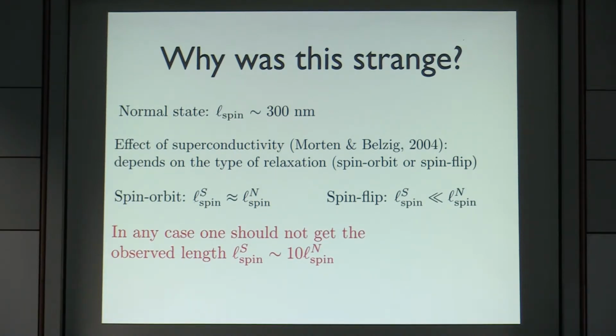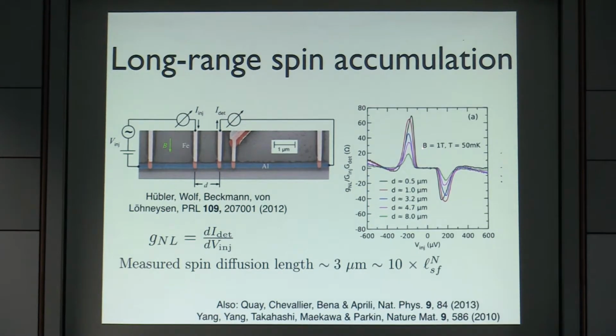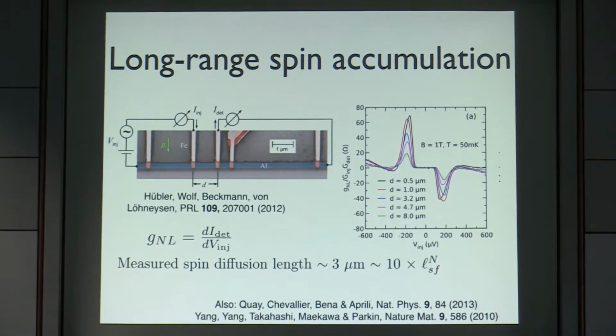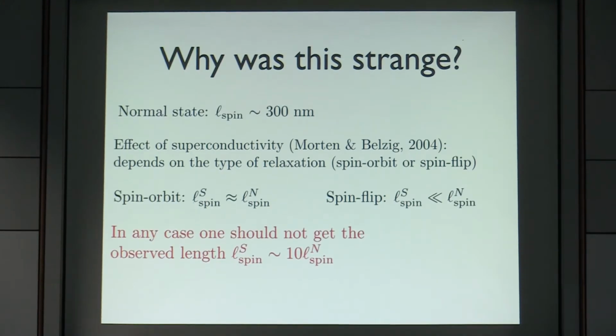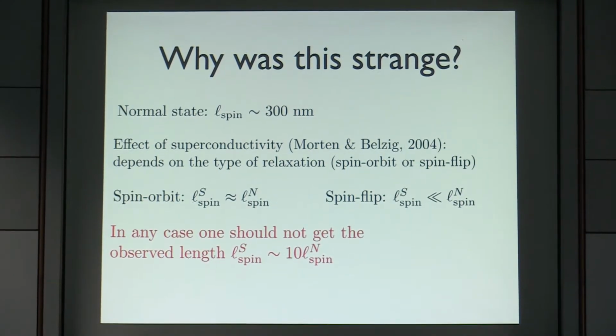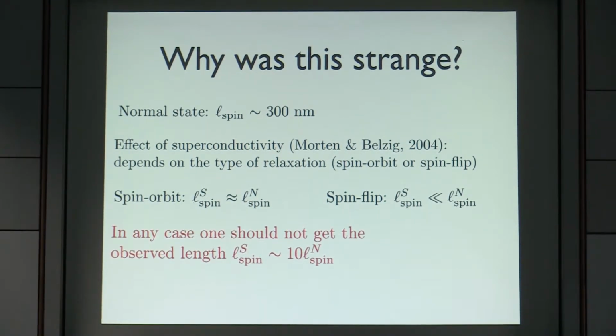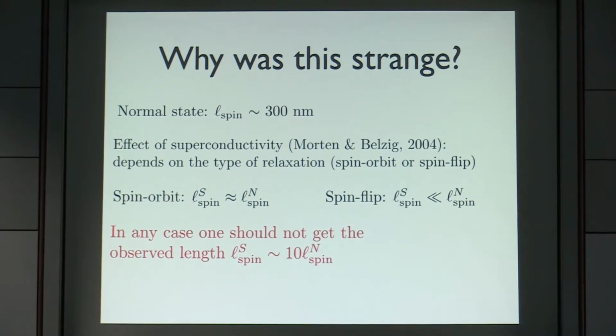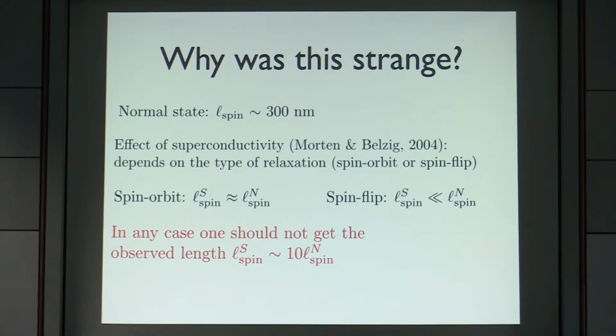Should be shorter? What's the reason? So they measure a spin signal here. I get this, but you expect the spin flip length to be shorter in the superconductor than in a normal metal. Can you explain very shortly why? These are theoretical predictions, the work of Morten and Belzig. Basically, you can calculate the collision integral for spin flip scattering, and then you look at the coherence effects on this, and this is the result. The physical mechanism behind these predictions, or qualitative, hand waving? Yes.